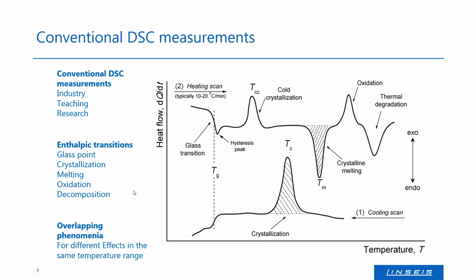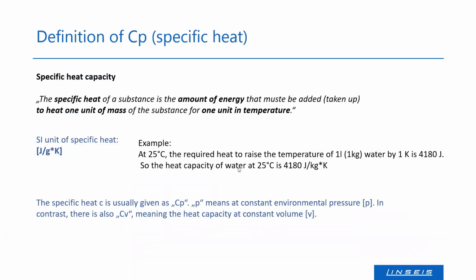But what we also can see here on this slide is there are some overlapping transitions, like the glass transition and the relaxation or the hysteresis peak. So they are overlapping, so it could be hard to get some valuable results from here. So this is what we talk about today.